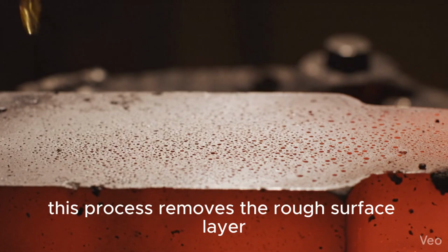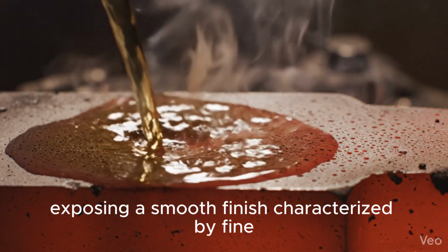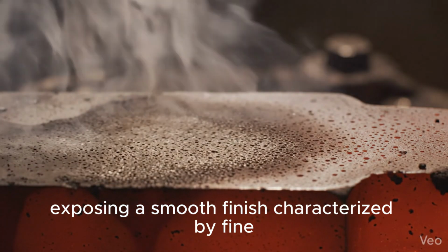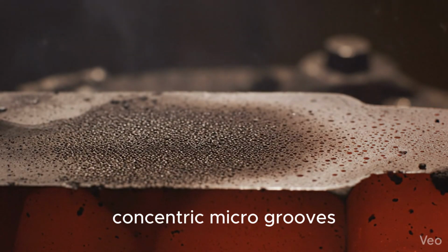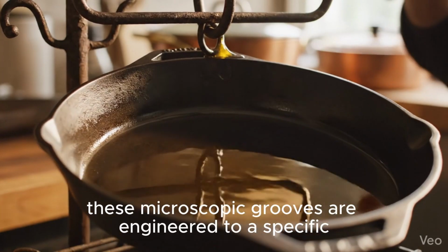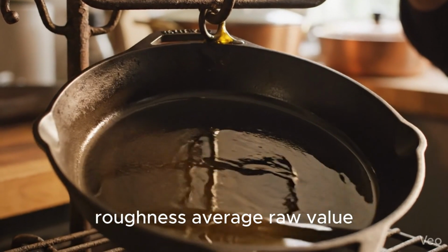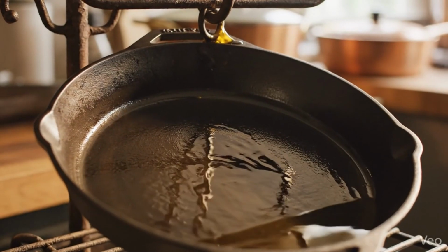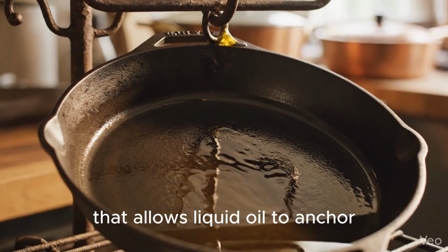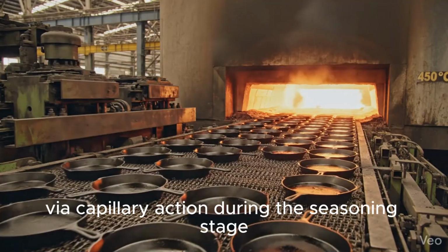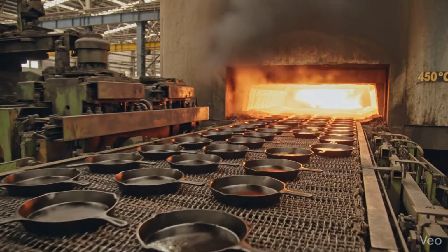This process removes the rough surface layer, exposing a smooth finish characterized by fine, concentric micro grooves. These microscopic grooves are engineered to a specific roughness average, Ra, value, creating an ideal texture that allows liquid oil to anchor via capillary action during the seasoning stage.